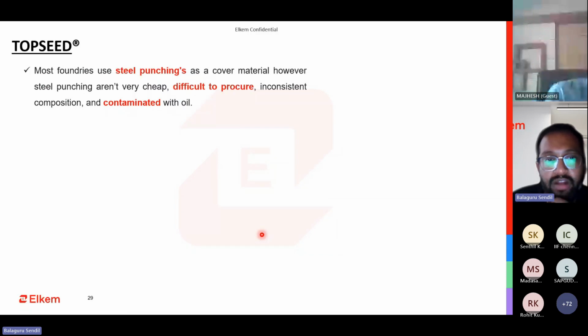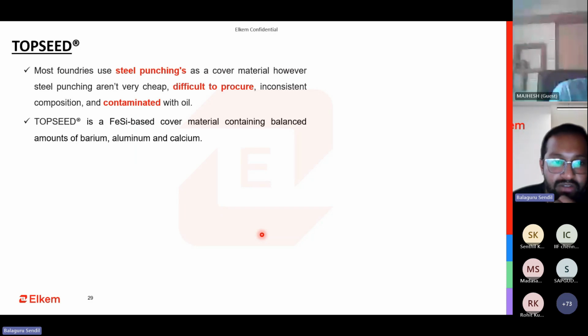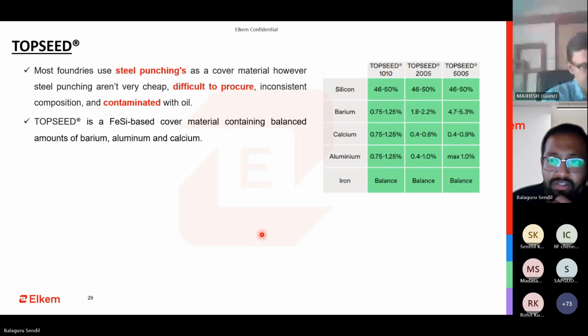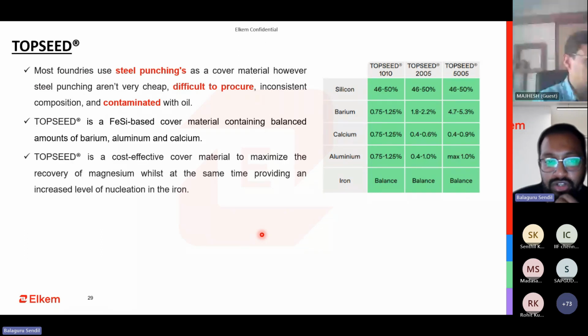We take a lot of care in making sure that the base metal is of good quality, and we put a lot of effort into that. But unfortunately, when it comes to the cover scrap, we tend to overlook it and we put some sort of contamination in it, which will actually spoil your base metal quality. So this is why we have Top Seed, which is our ferrosilicon based one. We have different grades of it. The advantage here is that this is of uniform size and chemistry, so you know what you are adding. You don't need any other foreign material coming into it, and it is extremely cost effective.